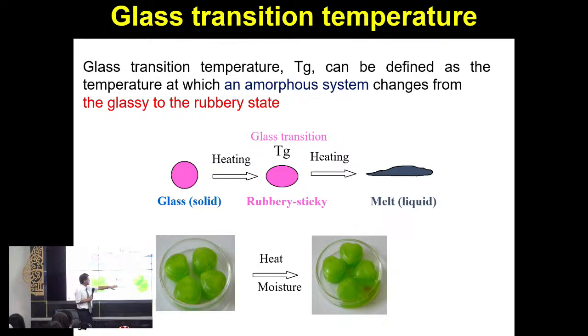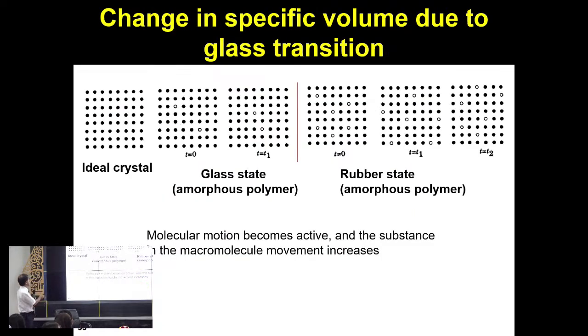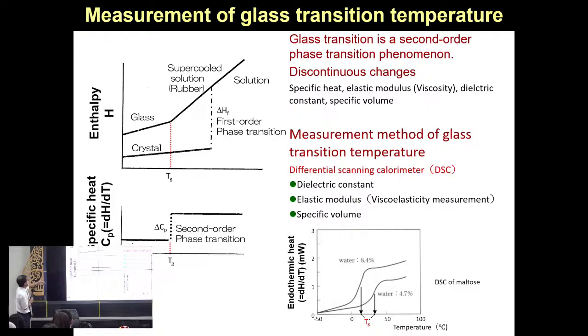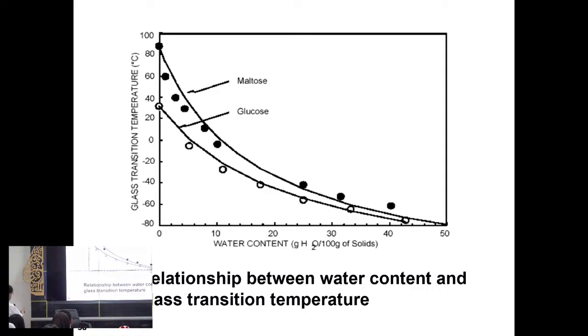So the candy and the aggregated candy, heat and moisture make the aggregated, sticky. So maybe you can measure it with DSC or another instrument. You can measure the glass transition temperature. So glass transition temperature depends on the water content. This is a maltose, glucose case. In the food powder case, glass transition temperature depends on the water content. So please remember, glass transition temperature depends on the moisture content.